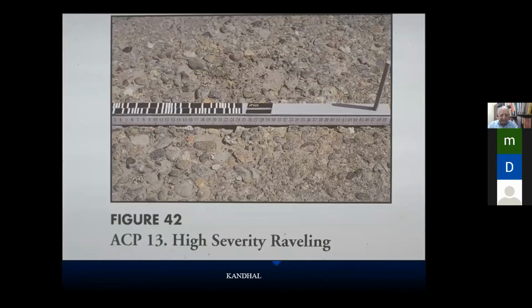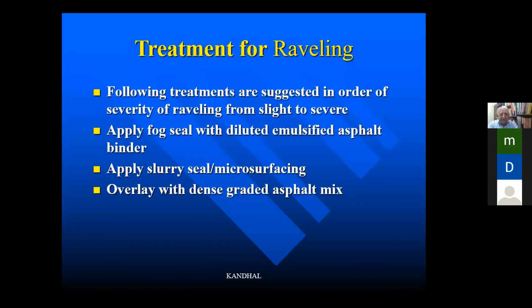Now here is a case of a high severity raveling. Now in this case, I not only have lost this sand, I've lost some bigger particles as well. You can see these pockets here. So I should have taken care of the raveling when it was slight, but I didn't do anything much to that. Now it has become so bad. It has become severe here. So how do I treat the raveling? Now the following treatments are suggested in the order of severity of raveling from slight to severe.